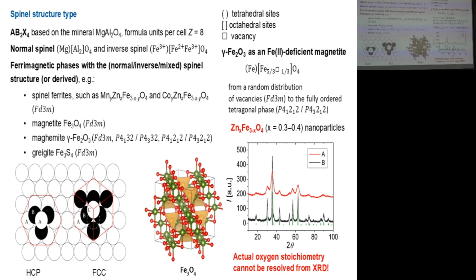And there are two types of cations, let's say A and B, and the A represents cations that enter the tetrahedral sites, and B describes cations that enter the octahedral sites. So we have one tetrahedral cation, two octahedral cations, and four anions. So in the normal spinel structure, this tetrahedral cation is a divalent cation like magnesium 2+, and the cation entering octahedral sites is the trivalent cation like aluminium 3+. But it can also happen that the divalent cation goes into the octahedral sites and replaces half of the trivalent cations, which then go to the tetrahedral sites.